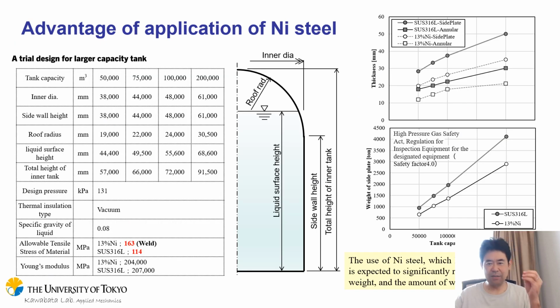Also, we discussed the advantage of applying Ni steel with high yield strength. The right-hand side graph summarizes the benefit of nickel steel. According to the tentative simplified calculation, the total weight of the side plate is reduced by 30%. So this slide shows that by using 13% nickel steel, the total weight of the side plate can be reduced by 30% compared with stainless 316L.